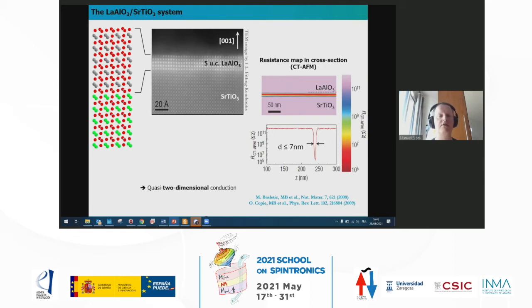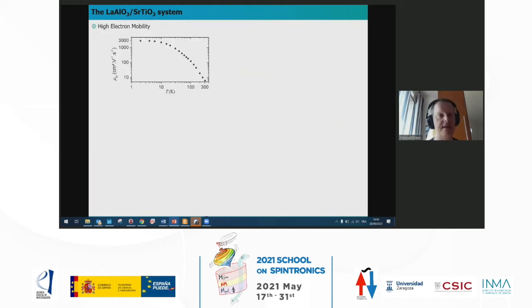We made a conductive atomic force microscopy image of the 2DEG in cross-section, and we confirmed that it is very, very thin and very conductive. Thickness was a few nanometers. Here we have some convolution effect by the tip, so it's probably on the order of a few nanometers, 2-3 nanometers maybe. And this 2DEG has a lot of interesting features.